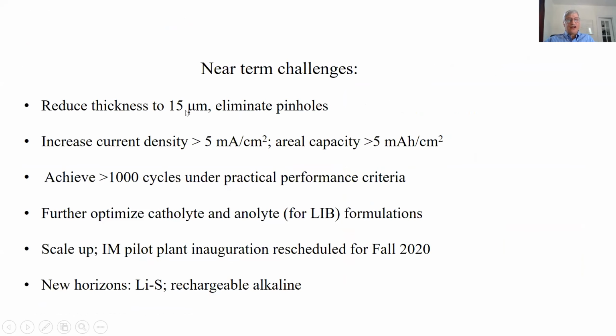So with the near-term challenges, we want to get the thickness down to even lower, about 15 microns without pinholes. We want to get even higher current densities. And we're at about 800 cycles. We want to get above 1,000 cycles under practical performance criteria, meaning high current densities and high capacities.